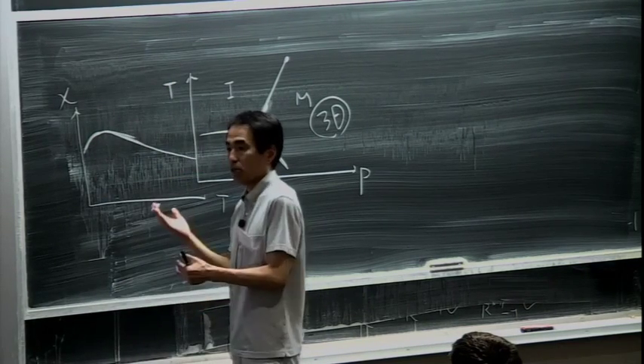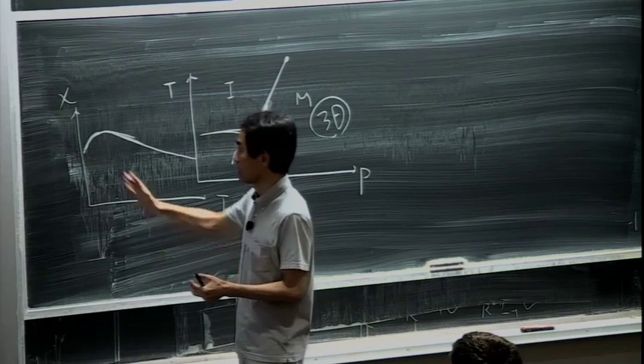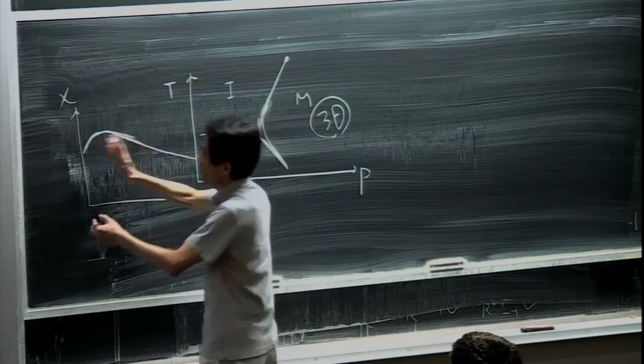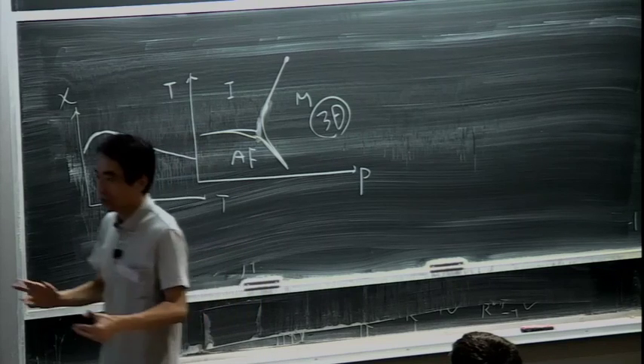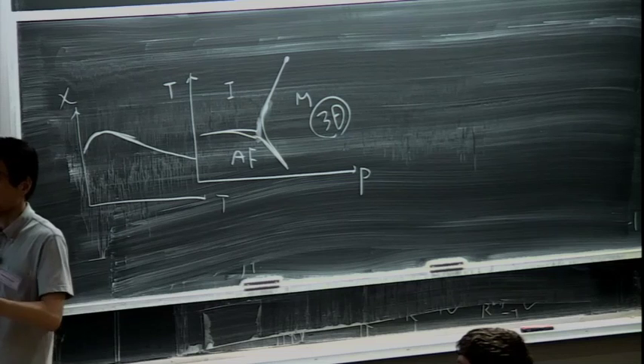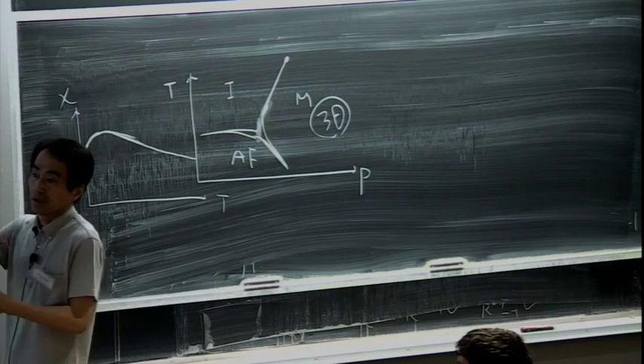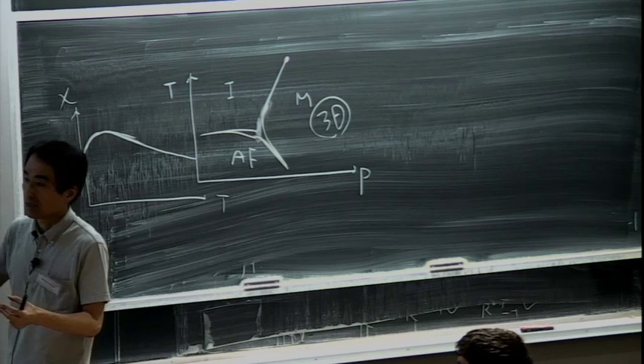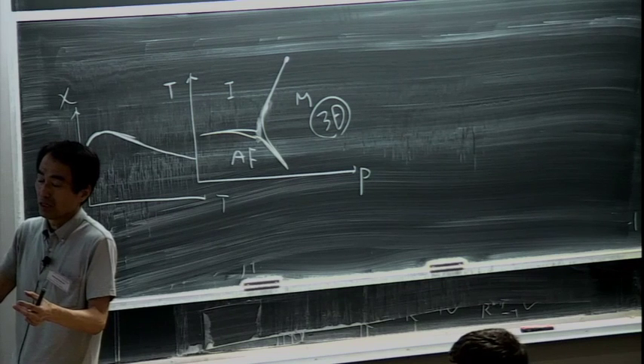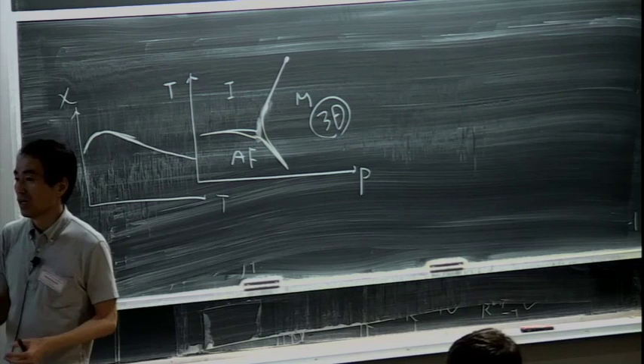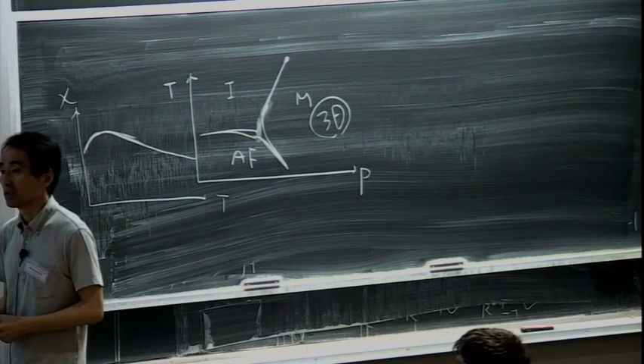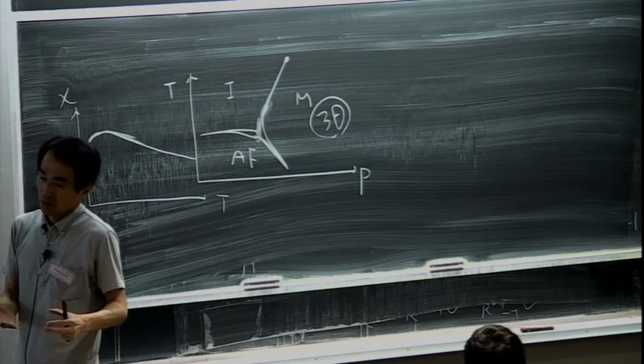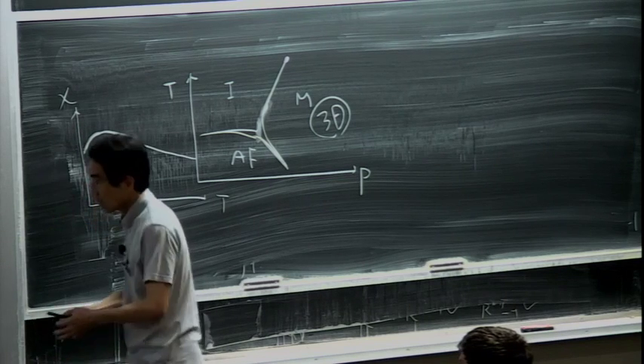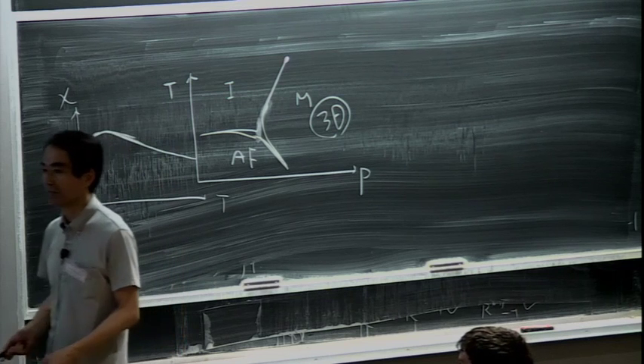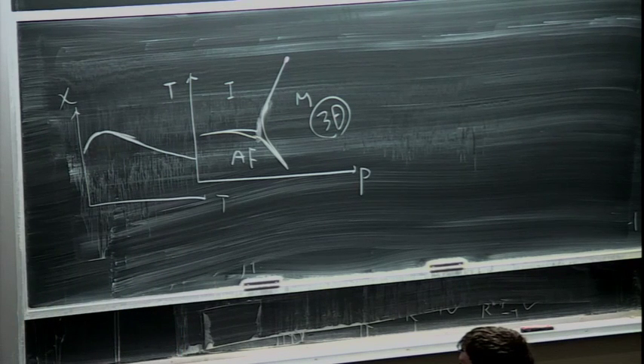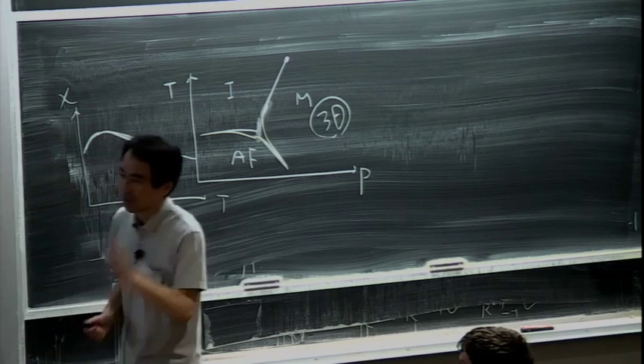And this data is well reproduced by the triangular lattice Heisenberg model. This means that at high temperatures, maybe around this temperature range, the short-ranged 120 degree spin configurations are fluctuating. But at low temperatures, maybe the 120 degree ordered state is not stabilized, so with no ordering, some ferromagnetic state occurs. So maybe there should be some crossover between this high temperature state and the low temperature ferromagnetic state. So this peak can be a crossover from bosonic excitations to the ferromagnetic excitations. This is a guess.